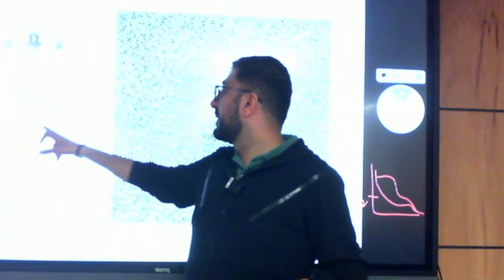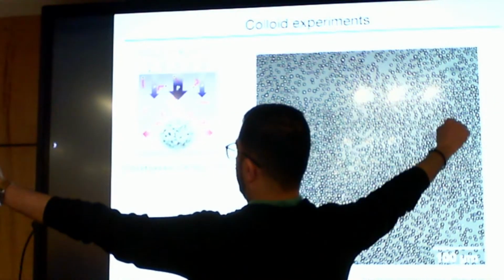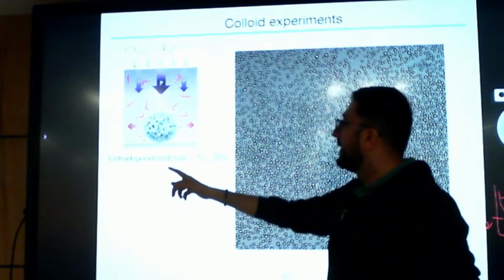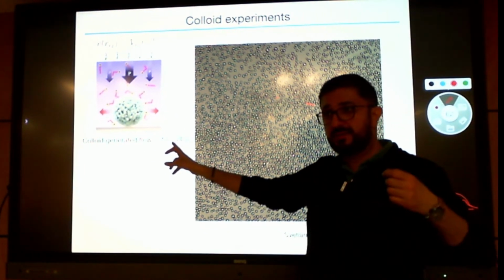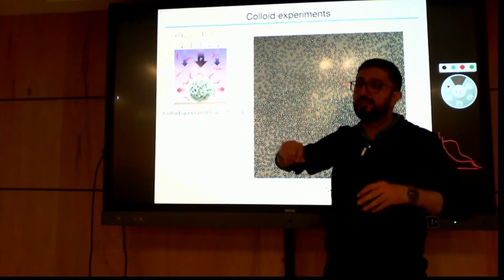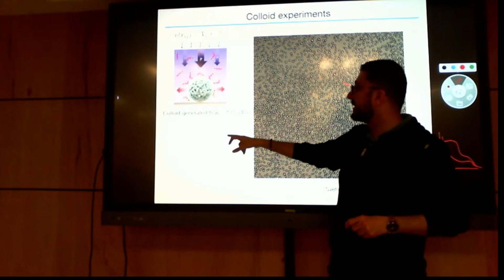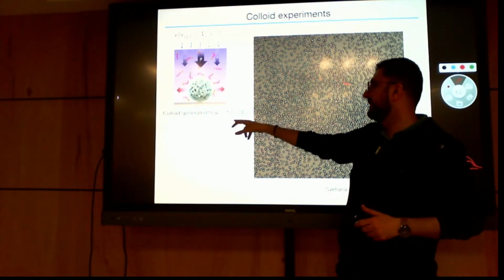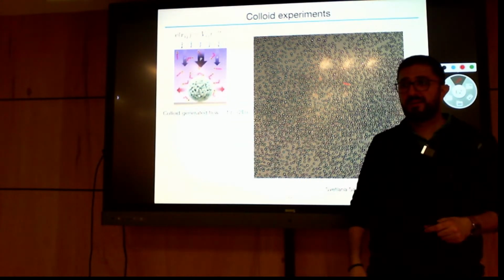But we know that in 2D, due to Stokes, if you have incompressible fluids, the colloid-generated flow is like a flow monopole, okay? This creates a flow field that pushes the flow outside. We know that this flow field has to be 1 over r in 2D. Otherwise, you cannot solve the Stokes equation for strictly 2D. In 3D, it's 1 over r squared. And if we have a quasi-2D system, we expect something between 1 over r and 1 over r squared. Isn't that what we have in our model? That's exactly what we have in our model.